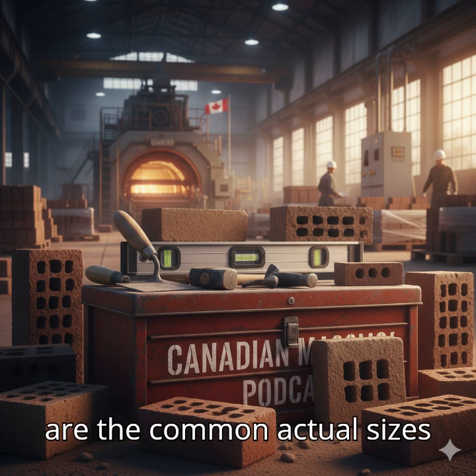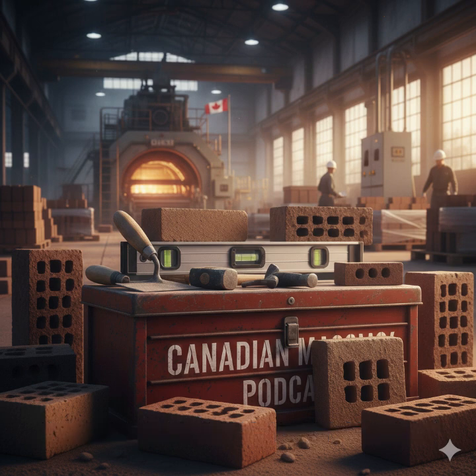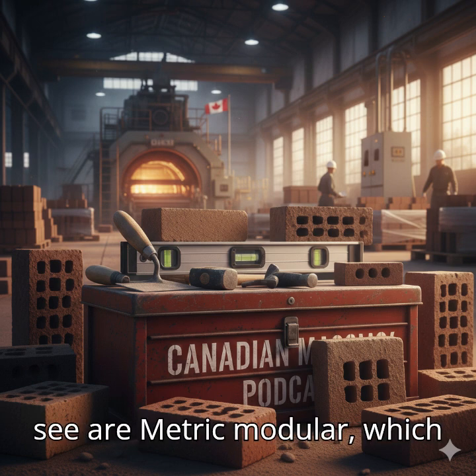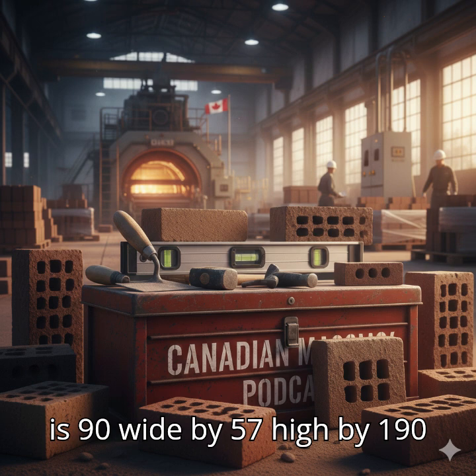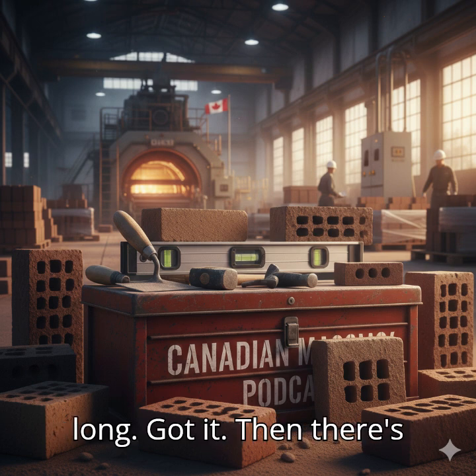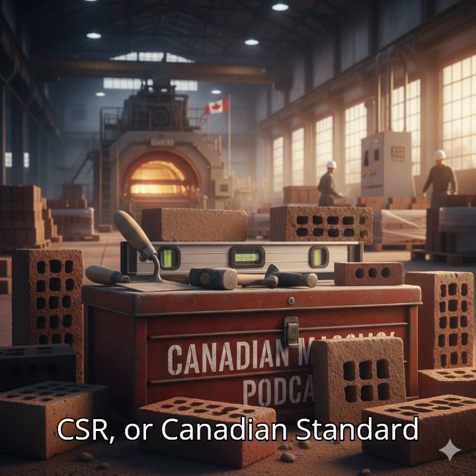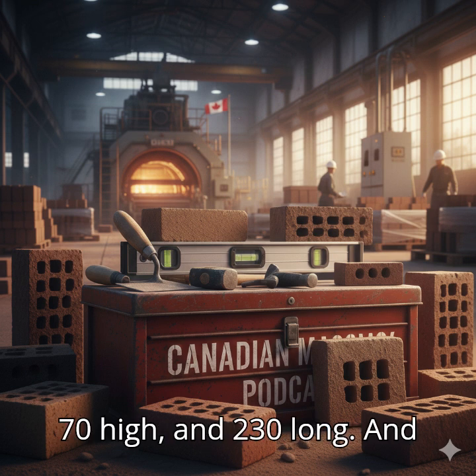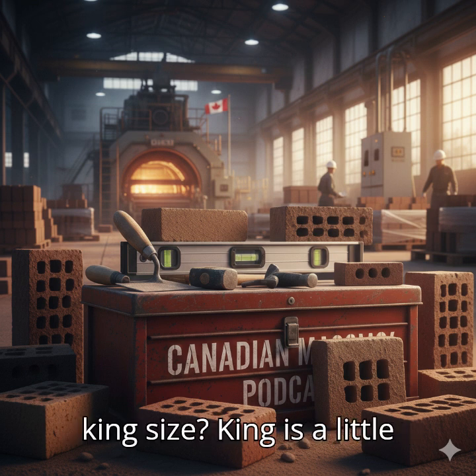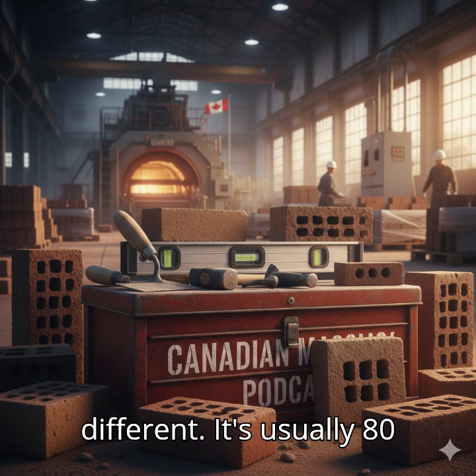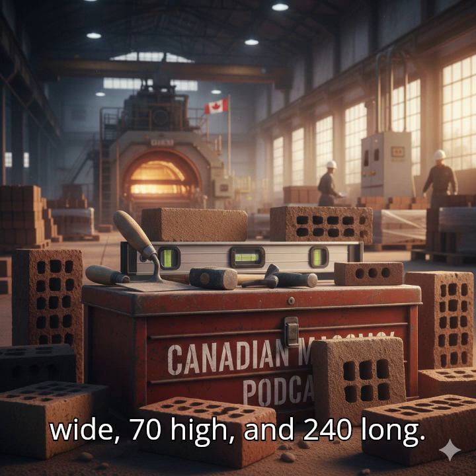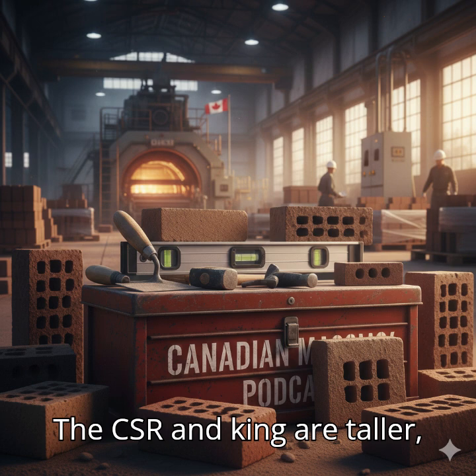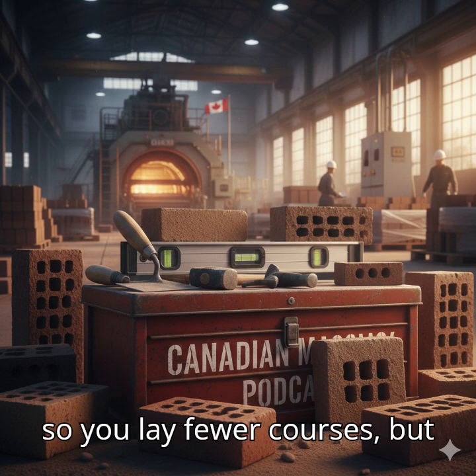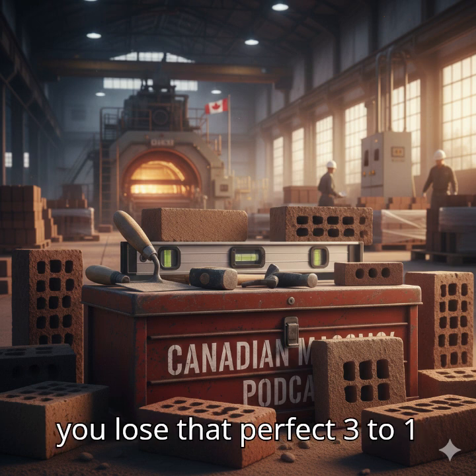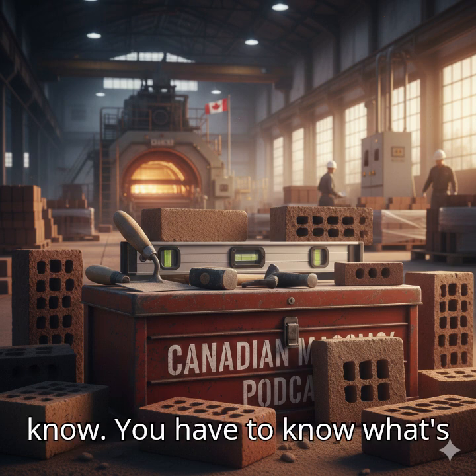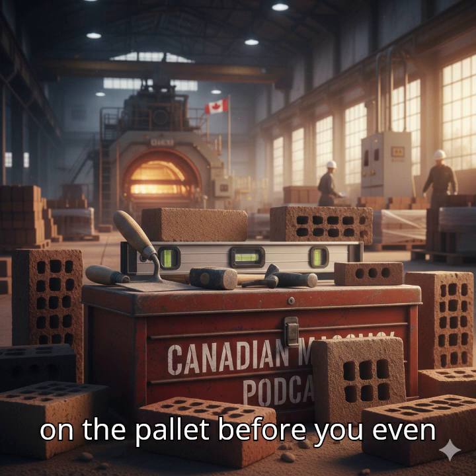So what are the common actual sizes we need to have memorized? Okay, the big 3 you'll see are metric modular, which is 90 wide by 57 high by 190 long. Got it. Then there's CSR, or Canadian Standard Residential. That's 90 wide, 70 high, and 230 long. And king size? King is a little different. It's usually 80 wide, 70 high, and 240 long. The CSR and King are taller, so you lay fewer courses, but you lose that perfect 3-to-1 alignment with block. Good to know. You have to know what's on the pallet before you even start.